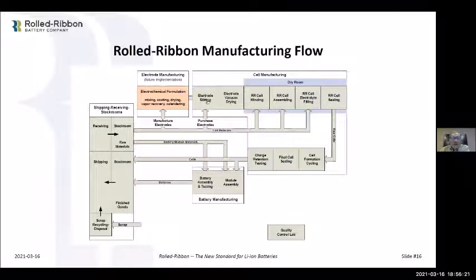We then slit the electrode. Our slitting process is a little different because we have the narrow ribbon versus the wider ribbons they use. At the end of the day, we use the same equipment, so it's identical. The only stuff that's different is really the very back end of the cell production. Our winding process, you saw that the Z fold makes us different. So rolled ribbon cell winding is different. And of course, our assembly process is very different from what they have. Because of all of that, our electrolyte filling is different, and then how we seal it up at the end of the day. So the very back end of the process is different, but everything up to the winding of the cell is identical to the way any lithium-ion cell is made in any other factory.